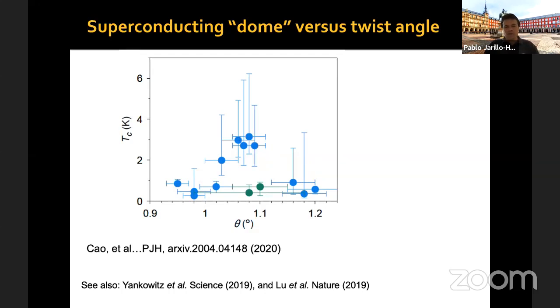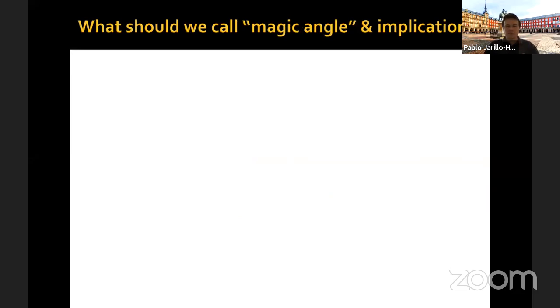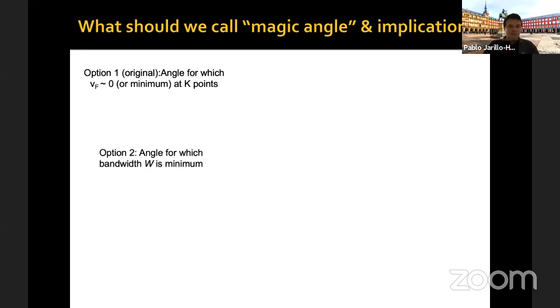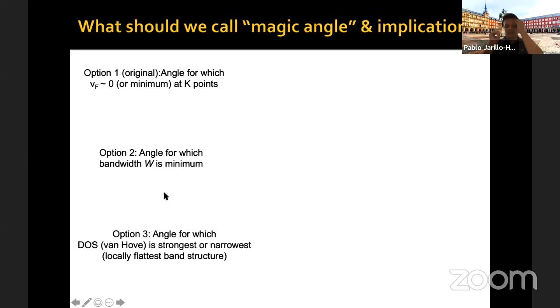And this leads us to the following question: what should we call magic angle, and what are the implications, okay? From a theoretical point of view, you could argue, why don't we take the original definition, which is the twist angle for which the Fermi velocity is zero or minimum at the K points, okay? Now, there is also another definition possible, which is the twist angle for which the bandwidth of that flat band is smallest, a minimum, okay? It turns out the angle for which this happens is not the same as the angle for which the other happens. And then there is another definition: the angle for which the density of states, in particular the van Hove singularities that occur in these flat bands, are strongest and narrowest. So these are the ones for which locally the band structure is flattest, not globally in momentum space, but locally in some momentum space region.